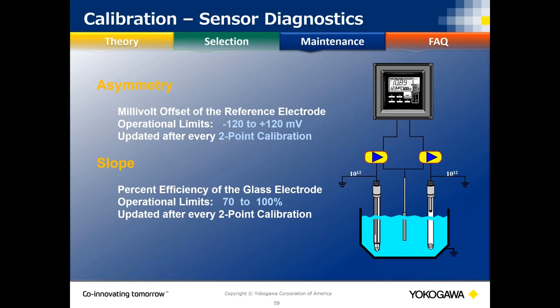But again, most analyzers, anywhere from 60 to 120 will alarm. 85, if your offset is that, when you put it in your 7 buffer, pay attention because you're compensating about a pH and a half in from where you actually are, and you don't really want to maintain that way. Your slope, you get that after you do that second point. Alarms will be anywhere from 80 to 70%. They start out at 100. At 85, you're going to get sluggish readings. So at about 85, you're probably going to want to pull it, okay?